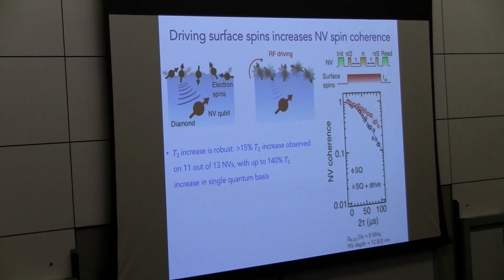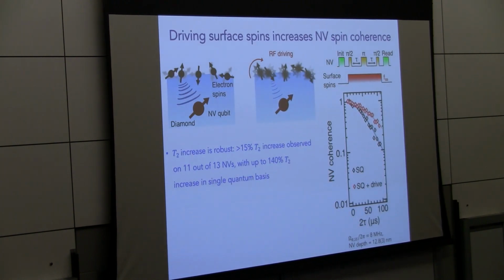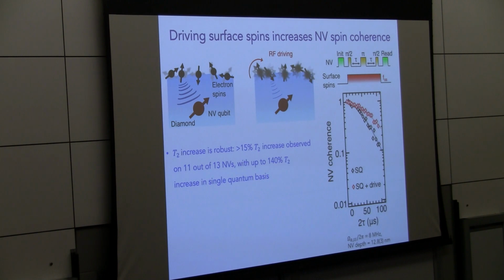Again, one could try to get rid of them, but people have been trying for a long time unsuccessfully. And even if you did, it's probably going to show up after some time again anyways. So what you can do, very counterintuitively, is start driving them. If I have these surface spins that are producing fluctuating fields, and I start driving them really fast, I can effectively motionally narrow their effect away. I can drive them so fast that their effect averages to 0.